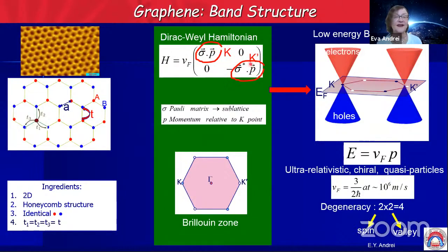Now notice that they are related by time reversal symmetry. So if electrons in the K cone go clockwise, sigma dot P is basically the projection of what we call pseudospin on the momentum direction, the direction of propagation. So in this cone here, they're parallel to each other. In this cone here, they're anti-parallel to each other. So this gives them a helicity, because sigma dot P is basically what we call the helicity operator.